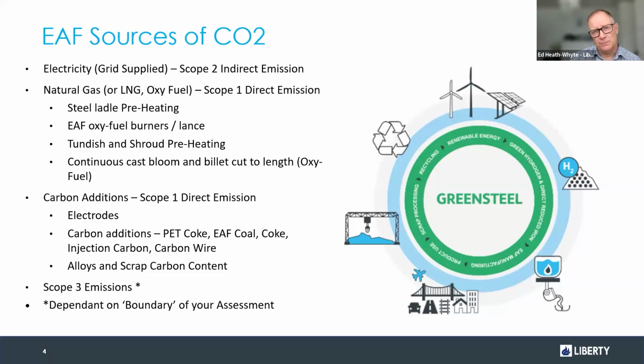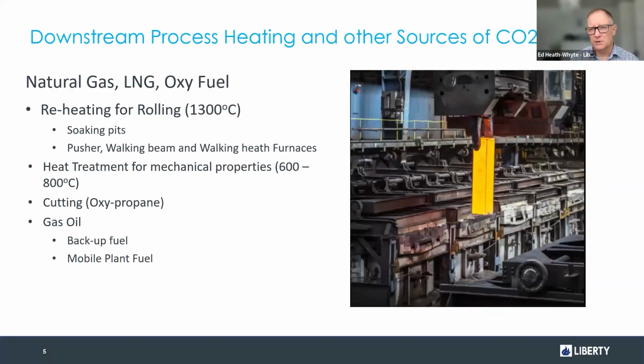And then as we process steel further downstream in our rolling mills, we reheat the steel, and we heat that up to 1300 degrees centigrade. And we use reheating furnaces, soaking pits, walking beam furnaces, walking hearth furnaces. We do heat treatment of steel. We cut steel, and we use gas oil as a backup sometimes, although not so much anymore. So we have quite a large usage of natural gas, particularly for reheating steel. And that's not generally understood. People think it's all in the steel making, but actually the downstream processing has a considerable amount of CO2 emissions.